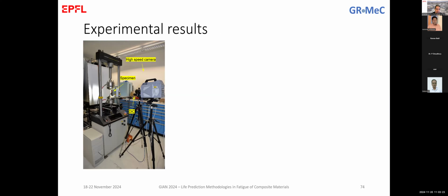So the setup is similar to what we had before. This is the same machine that we used before, but the chamber you see down there, we pushed it out of the machine. You can just take it out with some racks that we have here. And then the specimen is outside of the chamber. The reason for removing the chamber was because these specific specimens do not heat a lot. So we could do fatigue testing at relatively high frequencies of 10 Hertz without the problem of heating. We had a DIC camera to take photos and measure the full field strain on the surface, and we also had a high-speed camera that was used to identify the failure modes.